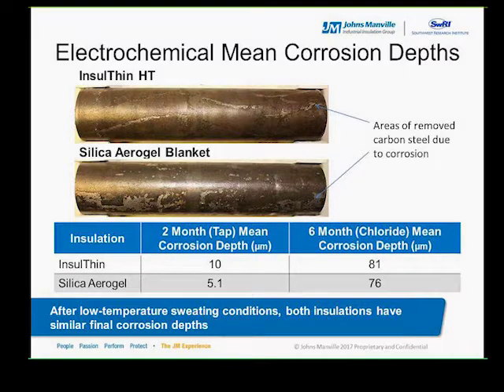The carbon steel pipe specimens were pressure washed to remove most of the corrosion byproducts, and you can see that both pipe sections look very similar with some corrosion affected areas, but otherwise the sections look fairly uniform. Keep in mind that the pictures are representative of the carbon steel pipes after exposure to both the 2 months of tap water and the 6 months of 1500 ppm chloride. So looking at the data table, the electrochemical test methods confirm that the mean corrosion depths for each installation were very similar. And based on SwRI's historical data and expertise, the depths were statistically the same for both of the installations at the 2 different time periods.